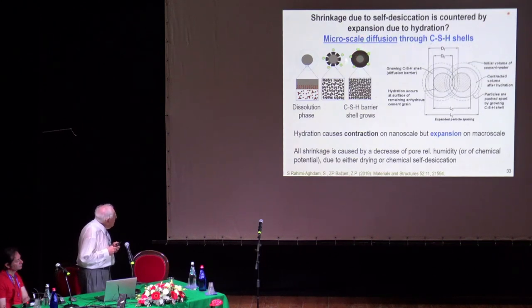Another complication has to do with scaling from hydration. So hydration within a day: the cement grain, anhydrous C3S, is enveloped by a continuous shell of CSH, calcium silicate hydrate. That has extremely low permeability, the CSH. And as it grows, of course, it slows down. But also what happens is that adjacent grains in the cement skeleton push against each other. So as these grains grow, they expand the skeleton elastically or in a creeping way.